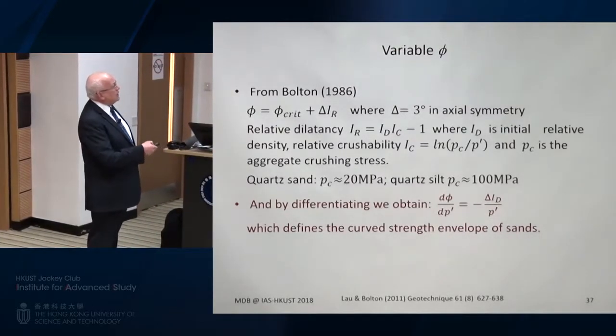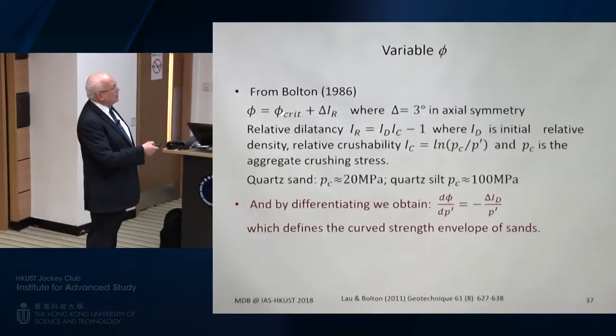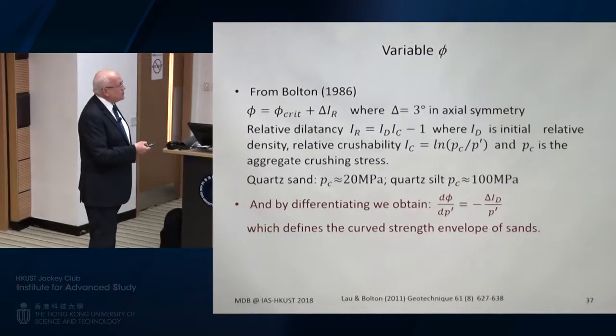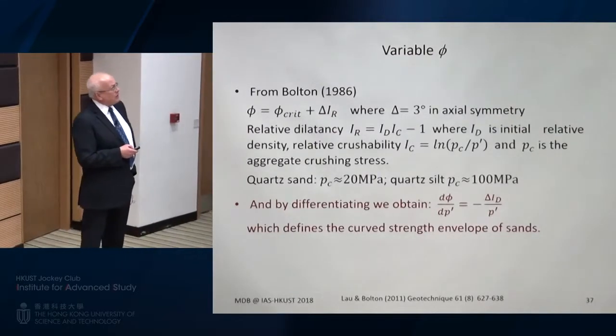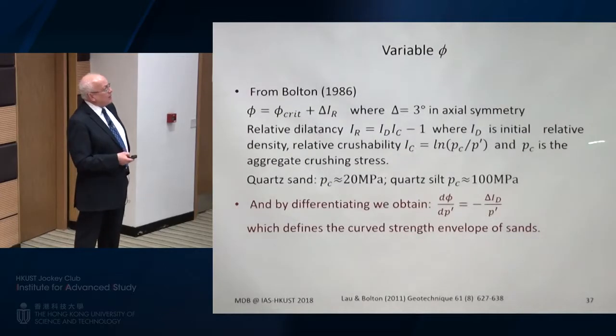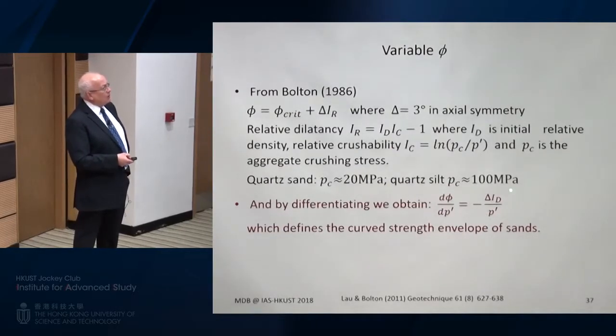So this is the equation we introduced half an hour ago. And what that is, as I showed you, is the nonlinear peak strength envelope. We've now established p_c values for the two materials: quartz sand, as ever, 20 megapascals; quartz silt, 100 megapascals. If you differentiate this, of course, what you get is d phi by d p dashed is minus delta, the 3 degrees, times the relative density over p dashed.